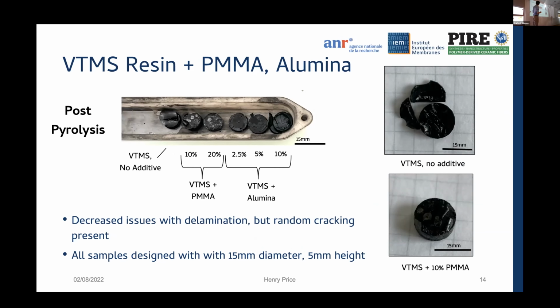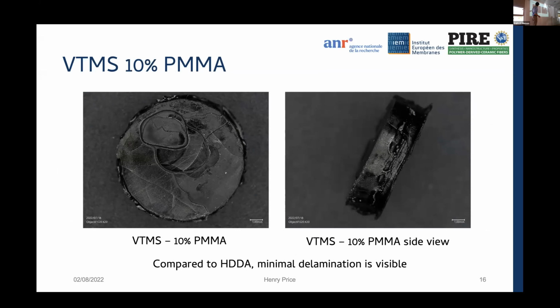Now some macro scale views. So as you can see, at 10% PMMA, in a side view, we really don't see this delamination. And also there's minimal large scale cracking in the samples. There were some slight cavity issues during printing, but generally a more successful sample overall.